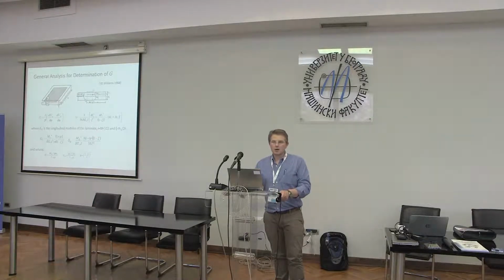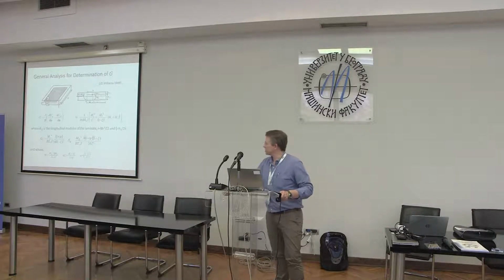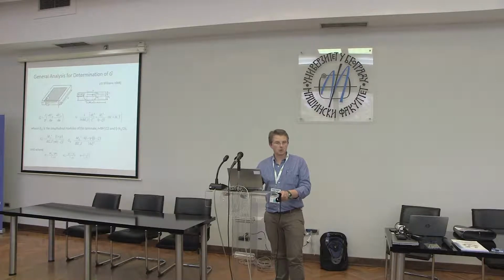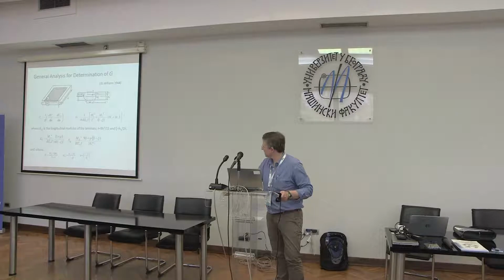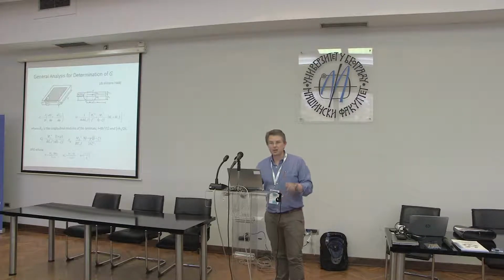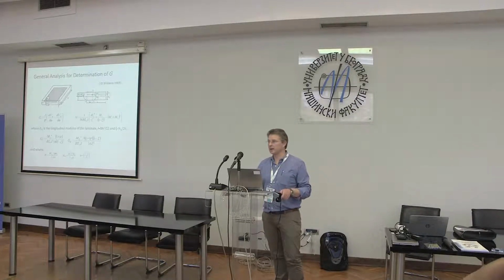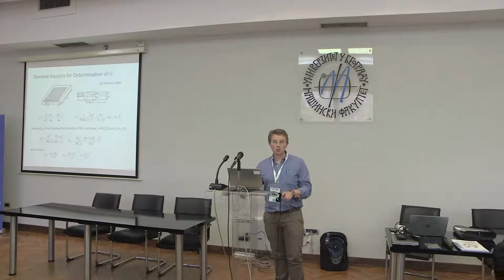So a really good way of analysing fracture in these problems was put forward by Gordon Williams in the 1980s, and he developed a generalised way of identifying and really establishing what the situation was with a crack in a laminate material, where you have only considered the global loading on the material.